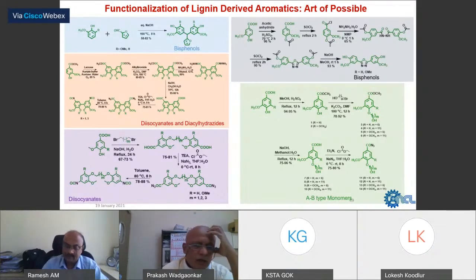I already told you, the world is looking for an alternative to bisphenol A. Bisphenol A is a very important monomer for polymer synthesis. But in fact, there are so many regulatory, health and safety issues associated with bisphenol A. So we have now positioned this bisphenol as an alternative to bisphenol A, which is made from acetone and phenol condensation. Now you can see here these two simple chemicals, furfural and guaiacol or syringol, reacted in a one-step synthesis by simple condensation reaction at 100 degrees centigrade. We were able to make this bisphenol.